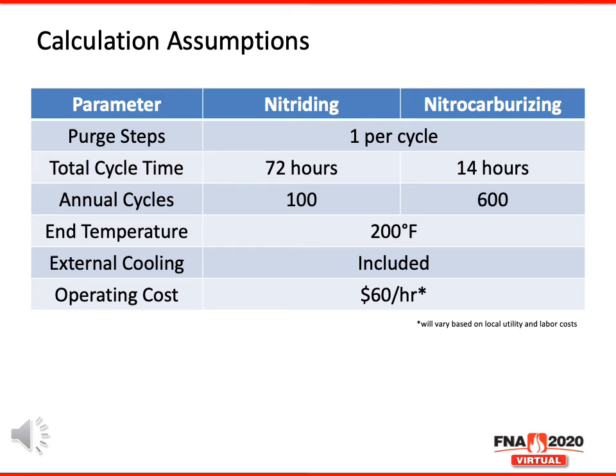Both a nitriding and a nitrocarburizing cycle typically could be performed in the same furnace. We're assuming, for the sake of our conversation, the purge step would be 1 per cycle. The total cycle time on a nitriding cycle, again, these times will vary based on a particular process or need, but a good average time might be 72 hours for a nitriding cycle, and maybe 14 hours for a nitrocarburizing cycle in this style of furnace.